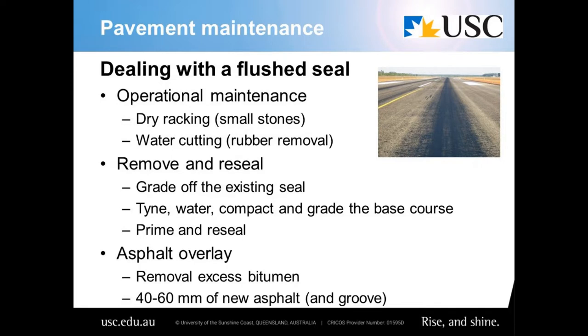In terms of just keeping the runway operational and safe, you can certainly dry rack, so just putting on some additional small size stones and rolling them into the surface. What quite often can happen is that those stones will stay well held during summer, but when you get back to winter, a lot of those stones will sometimes become loose and potentially become small pods, so it does need some management. That happens usually in winter because the bitumen then hardens back up, and you don't maintain the bond between the stones and the bitumen film that's free on the surface.